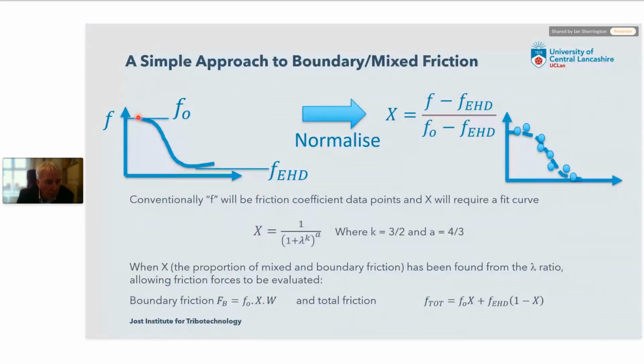So this is the method. Normally we can start off with some measured data or a Stribeck curve like this. It doesn't need to be our own data. It can be data from someone else's work. And what we suggest is that this friction data, this Stribeck curve, is normalized to produce a parameter x, which varies between 0 and 1, and tells us the proportion of mixed to boundary lubrication. We can normalize it by dealing with the y-axis here. We can subtract this fluid film friction from the boundary film friction to generate a number which varies between 0 and 1 if we subtract this limit down here from the friction at the point of lambda where we want to operate. And what we find is that this equation for x, if we adopt real data like this, turns out to be very nicely modeled by this equation here.